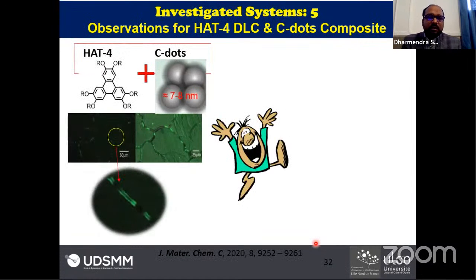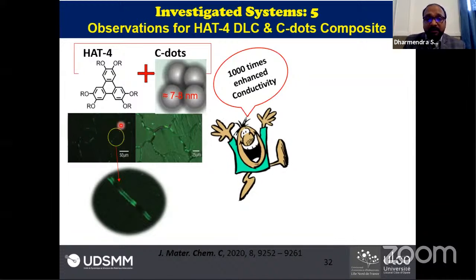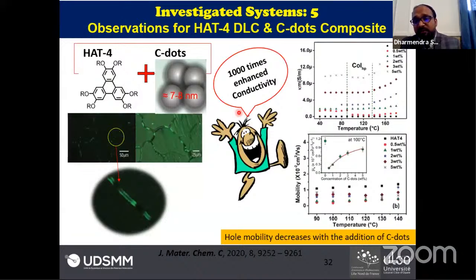And later on, we also dispersed some carbon dots in different HAT matrices. In this study, we dispersed some carbon dots of size 7 to 8 nanometers in diameter in the HAT4 matrix. Because these nanomaterials have a characteristic to form self-assembly or self-networking, we found that these carbon dots prepare a self-assembly in the HAT matrix. And very interestingly, its conductivity enhances 1000 times. However, due to the changes in molecular ordering, we obtain slightly lesser charge carrier mobility here.